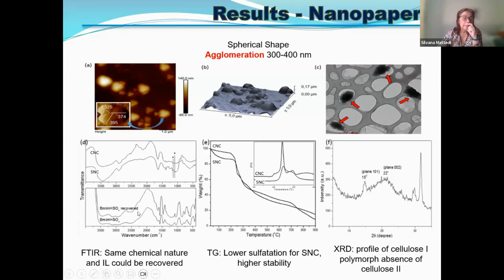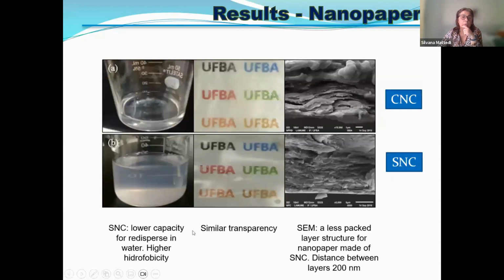So what you see when you recover the solution is that the same FTIR profile is recovered, so we can reuse it a lot of times. And we produced papers with this material. What we are interested in here is transparent papers. We used to use acetate film a lot to present at conferences, but now we use the computer more, so it's not common anymore.